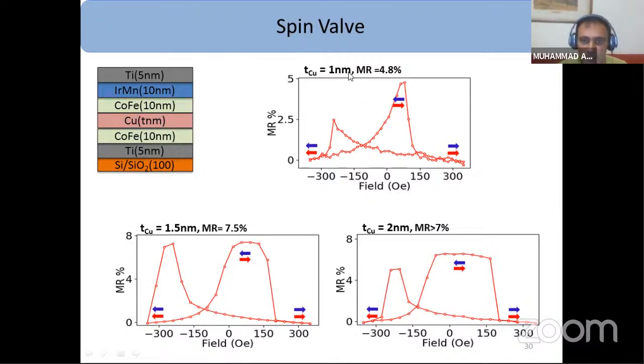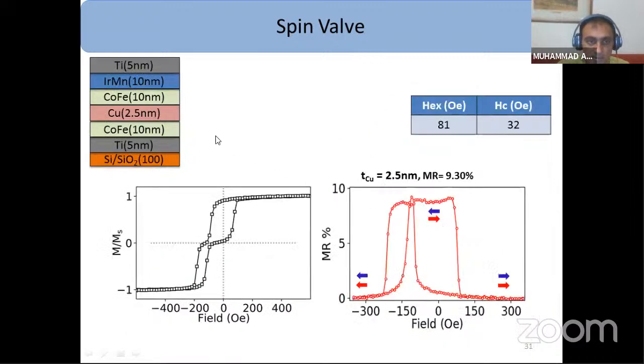For the copper, 1 nanometer, I have got an MR value of 4.8. Then I increased the thickness to 1.5, and the magnetoresistance increased. As the thickness further increased, I got more than 7%, and for a thickness of 2.5, I got an MR of 9.3%.